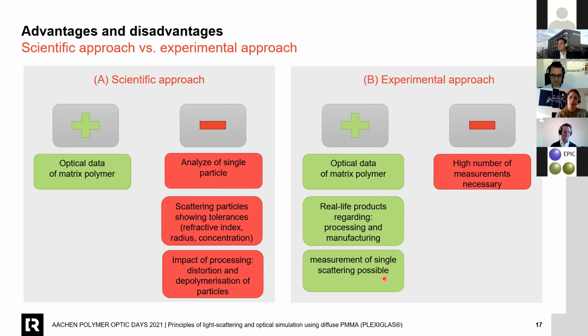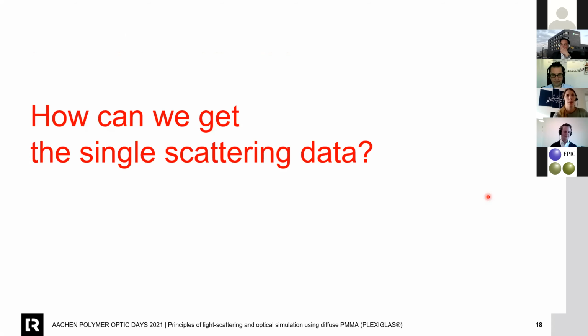And because we can dilute our concentration of single scattering particles, we can measure the single scattering. And everyone who has a goniometer or an injection molding machine and knows the matrix material without the scattering particles can do this experimental approach as well. The disadvantage of this approach is that you need a high number of measurements because you have to be sure to measure the single scattering.